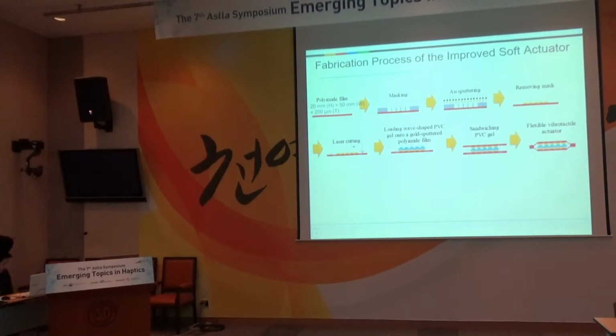First, we prepare the polyimide film with a thickness of about 200 micrometers. Then we apply the aluminum masking, and then we sputter gold onto the mask and the polyimide film. By removing the mask, we can get the polyimide film with the patterned electrode. After that, we make this spring using laser cutting, and then we put the PVC gel onto the gold-sputtered polyimide film and attach the film to the surface of the PVC gel like that, and finally we can get the actuator.